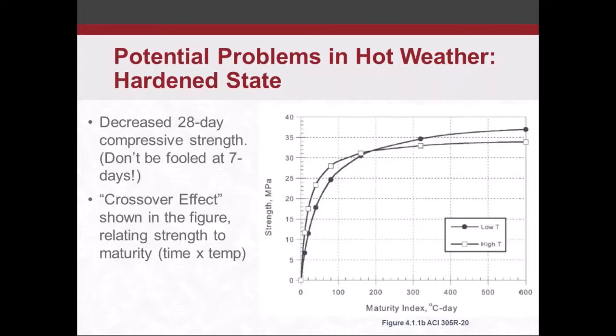Something else to keep in mind: decreased 28-day compressive strength at higher temperatures. We get what's called the crossover effect, and that's what's shown in the figure here to the right. And here we're relating strength to maturity, and the maturity is just a product of time and temperature. So if we were to keep time or age constant, you're going to get higher strengths with the higher temperatures, but eventually you get to this crossover point where those higher temperatures are going to be detrimental to the long-term, the later ages of concrete.